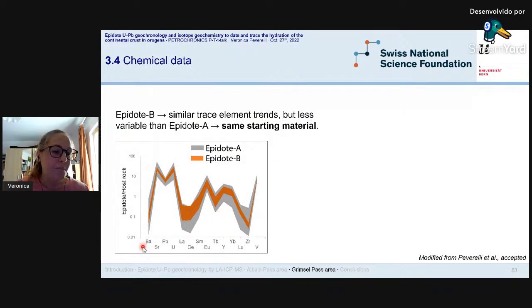So these are mass fractions of selected trace elements in epidote. We have both epidote A and epidote B. What's important for us is that, as you can see, the patterns between epidote A and B are basically the same, so they overlap chemically, but epidote B is less variable than epidote A, and this suggests that epidote A and B have the same starting material.